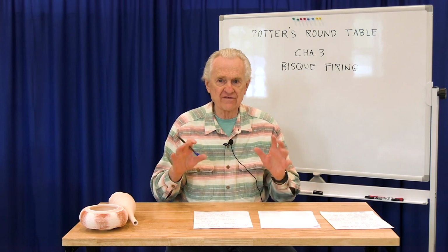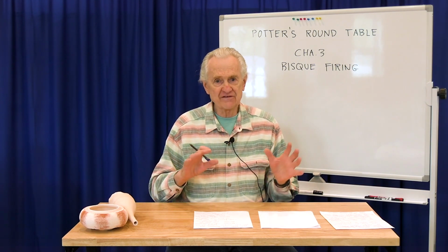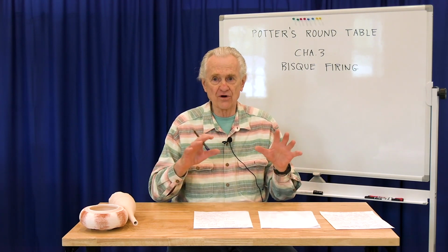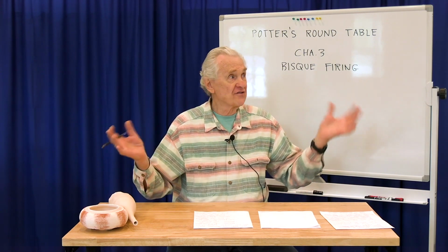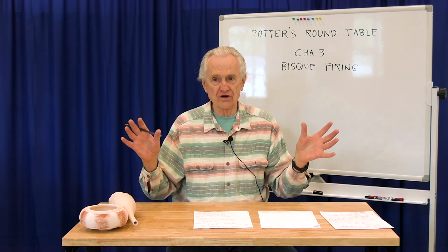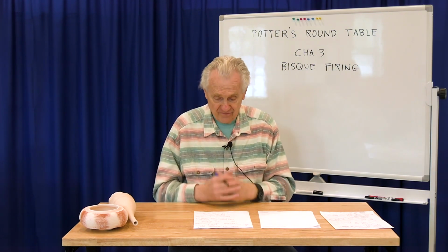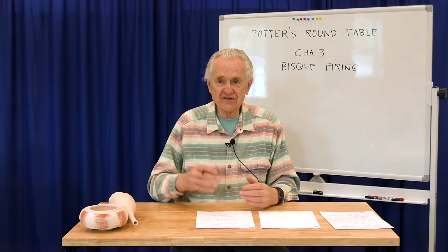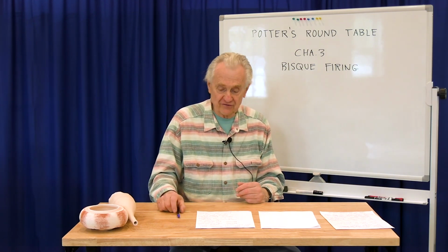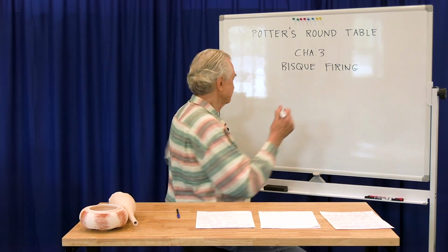This is a thin film of water molecules that's attached to all the surfaces in the clay. Even after the absorbed water has been removed, there is still a film of water molecules attached to the surface, the same way that everything in this room has a layer of adsorbed water molecules sticking to the surface of it, even though we can't see it. And the third kind of water is the chemical or structural water that's actually built into the atomic structure of the clay. Let me write a formula on the board here for a second.